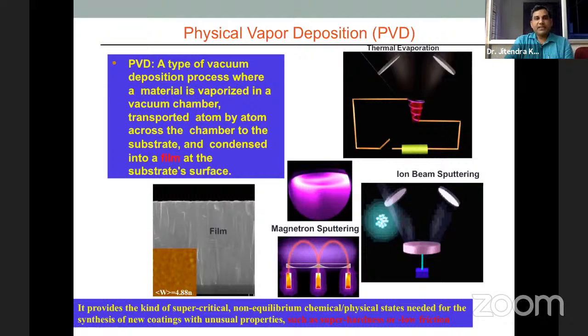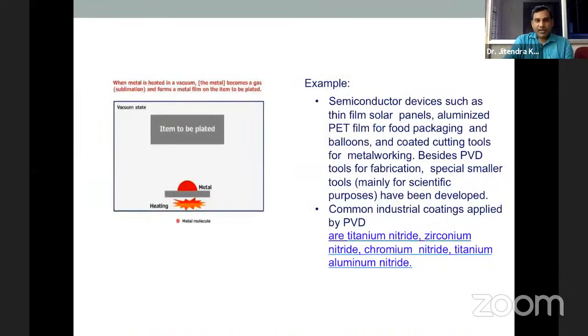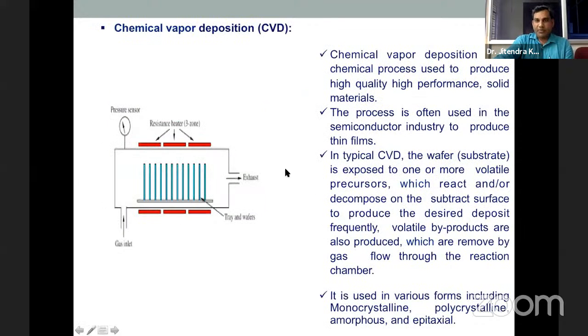So this physical vapor deposition is performed in a vacuum. So this is the example. Another process is chemical vapor deposition. We just provide the chemical precursors, and this is exhausted through the tray, with the resistance of the heater. In between, you just pass the gas inlet, and then according to that, we coat the material chemically.